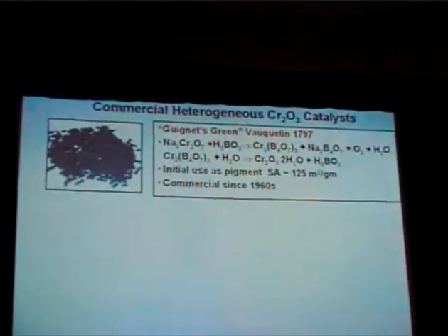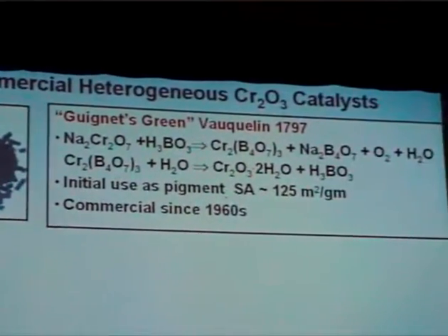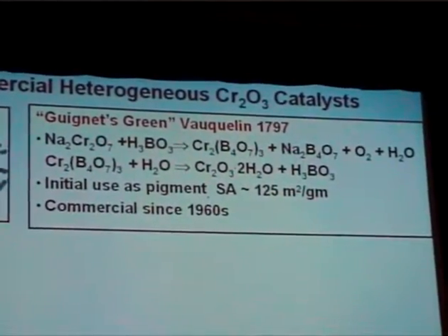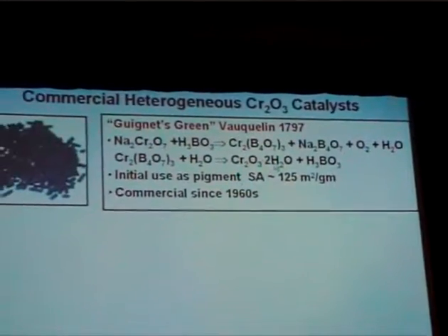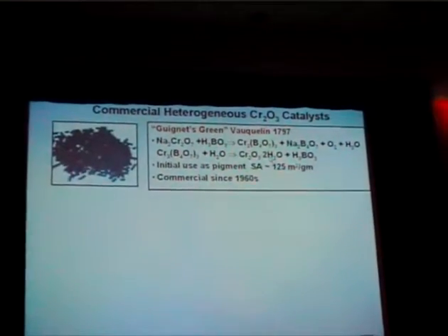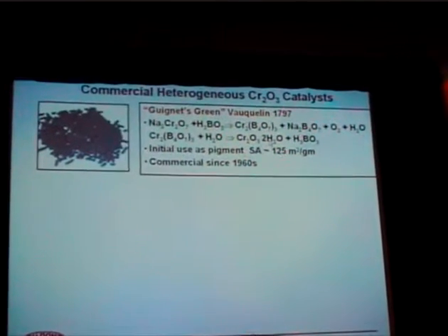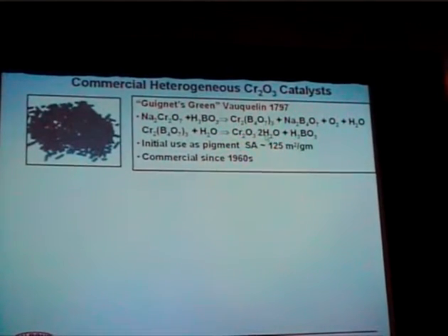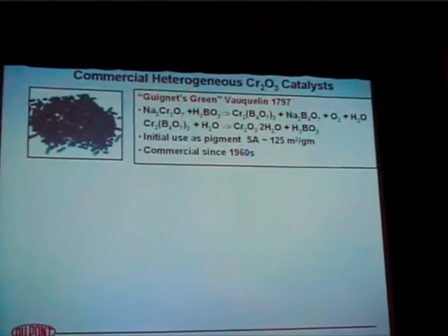The first one was this material, Guignet's green, which is actually a pigment. On my screen, it's a bright turquoise color. I don't know what it looks like out there. But it's made from boric acid and sodium dichromate. In a couple of steps there, you eventually make a hydrated Cr2O3, shown right here, which is then dehydrated to make a catalyst. And that has been used since the middle 1960s to make more fluorinated, highly fluorinated materials.